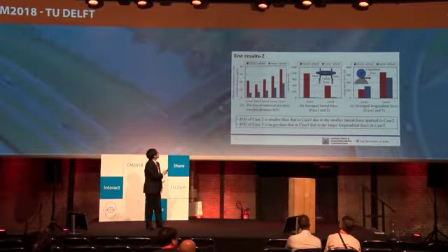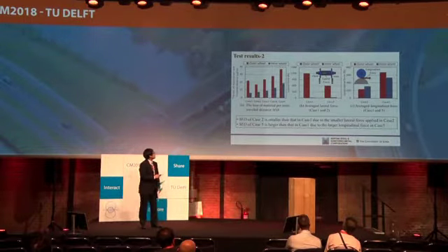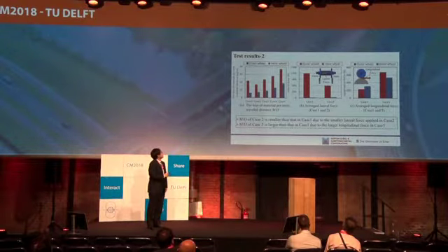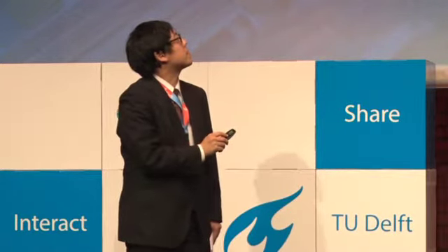This figure shows the loss of material per unit travel distance, m by d, compared across all cases. And the loss of material per unit distance of outer wheels is larger than inner wheels. And this embodies the value differences of all the cases.